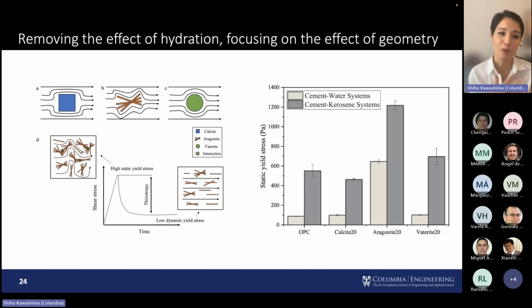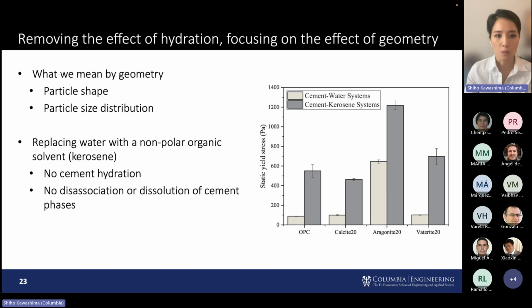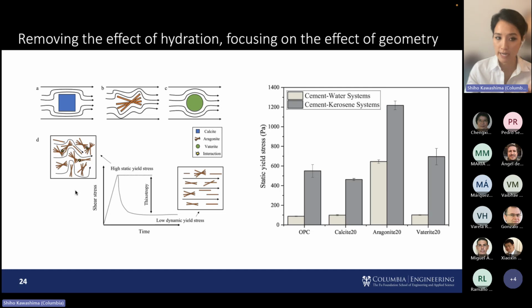And so, the way we visualize this is aragonite, they're needle-like. And because of the increase in specific surface area, they're able to aggregate together. And so through that aggregation, on the onset of flow, they can impose this resistance to stress. And so that's why it's driving up that static yield stress so much. There's also the impact of higher water demand due to the higher specific surface area. So all tied to shape, right? And because of these shapes, it also interrupts the flow line as well. So that's the reason why static yield stress is higher for aragonite.